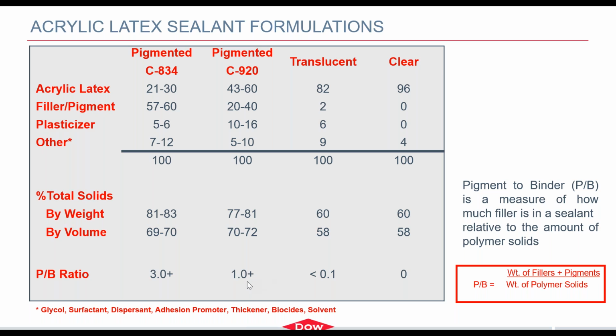Pigmented C920 sealants might start around 1.0. I've seen them as high as 2.2, 2.5 P to B. Translucent, because you have a very small amount of filler or pigment in there. Actually, typically just fumed silica will be less than 0.1, and then of course the clear does not have any pigment or filler in it, so it's 0.